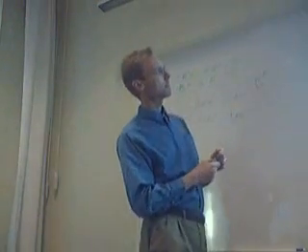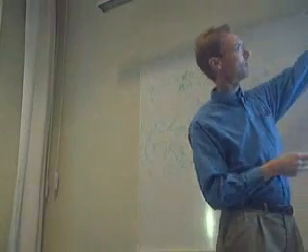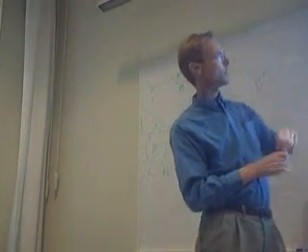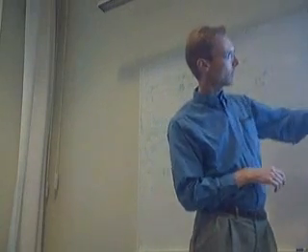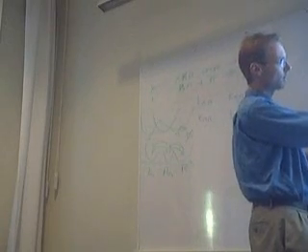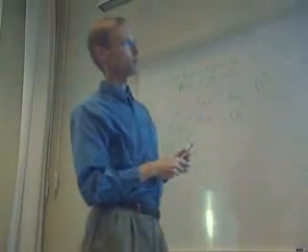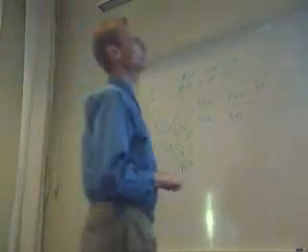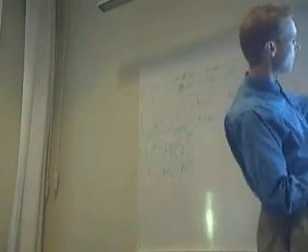And if we look at the chiralities, or the enantiomeric excesses, these evolve over time like this. So we have a number weighted one and a mass weighted one. If we plot the log against time, we get this region of linear growth, which is a straight line on the log graph, which means we've got exponential growth of the EE. And this is what the cluster size distributions look like, exponentially decaying.